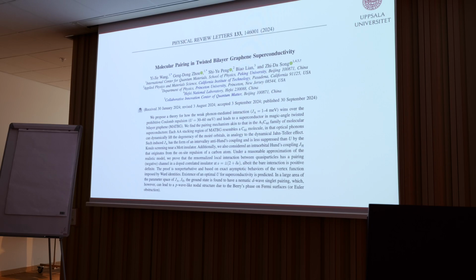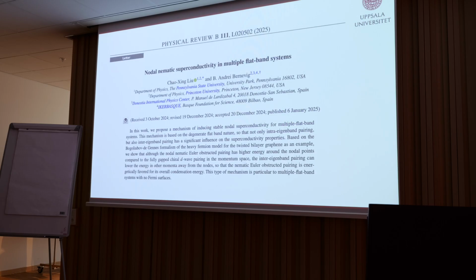Here's another work that assumed a rather different pairing mechanism of weak phonon-mediated pairing, very similar to some doped buckyball systems. And they also found a nematic d-wave spin singlet state with some nodal structure. So again, it seems rather consistent with what we found, but with very different starting assumptions. Here's yet another paper from this year, which looked into what's become known as a heavy fermion model for twisted bilayer graphene. If they assume big inter-eigenband pairing, they could find stable nodal superconductivity with a nematic order. So nematic order and nodal superconductivity seem to be popping up in a lot of different models.